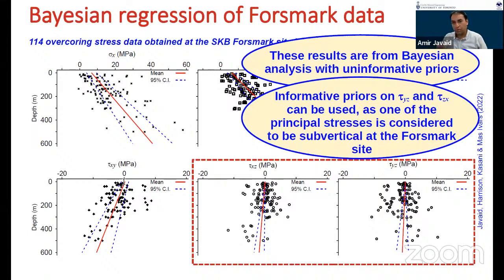Right. So if we go back to these data plots, you can see in the red box, we believe that in principle, since one of the principal stresses has to be vertical, the mean gradient has to be an intercept line practically at zero. If one of the principal stresses has to be vertical, then these two vertical shear components have to be zero.